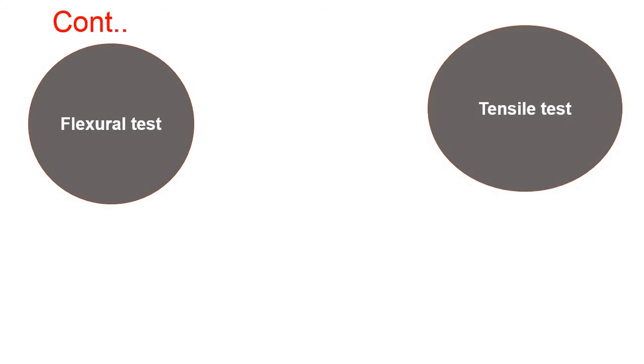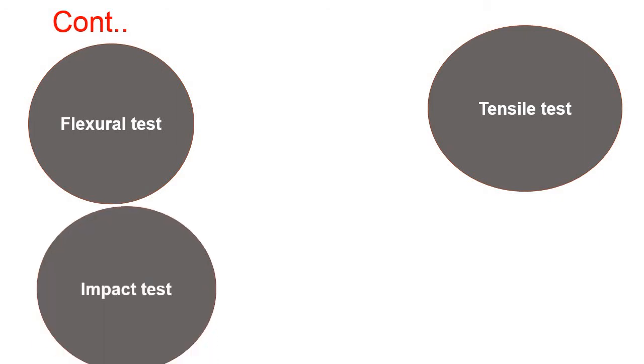In the tensile test we are using the ASTM standard D638/10. We are going to prepare a specimen with a dimension of 165 mm into 25 mm into 3 mm. The test was conducted in a universal testing machine with a gauge length of 100 mm and 5 mm per minute as the cross head speed. And then we will go for the impact test.